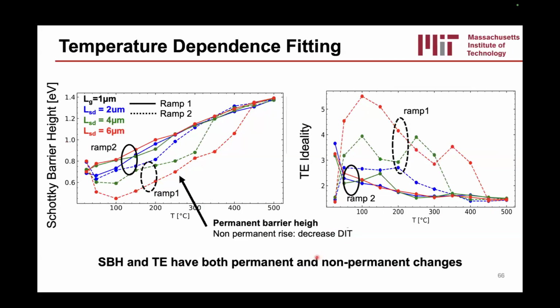However, we can look at things like the Schottky barrier height that we extract. And for the same set of devices, we can see that between ramp 1 in dashed lines and ramp 2 in solid lines, there is not only an increase in the Schottky barrier height, but a permanent change in the Schottky barrier height when we return to room temperature.